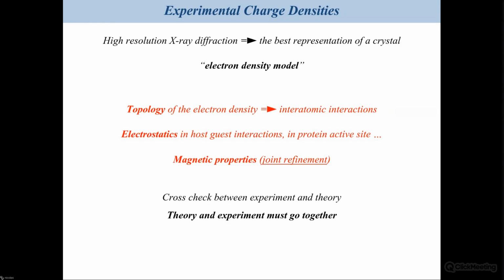And for that, we decided to propose what we call joint refinement. It means combining X-ray, neutron, and polarized neutron diffraction experiments together in the same model. And the aim was, among that, to be able to propose a very precise model that can be directly compared to the more precise theoretical calculations, because we imagine that theory and experiment must go together.